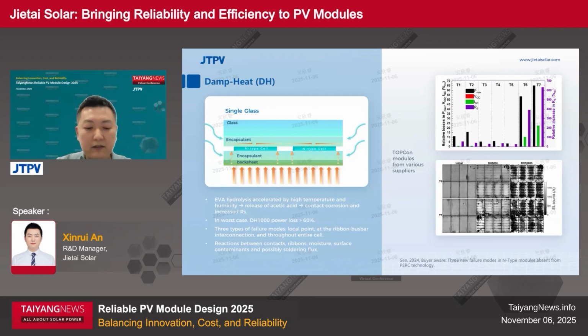The EL images show that at least 3 different types of failure patterns exist that include the localized point failure and failure around the contact ribbon areas, and also the failure throughout the entire cell surface. The point failure is attributed to the chemical reactions between cell contact, moisture, and some local contaminants. While the interconnection failure originates from the chemical reactions between the contact ribbons and possibly the soldering flux that involve acetic acid release. And the last failure for the entire surface is not contact related, but maybe due to some limited types of encapsulant.